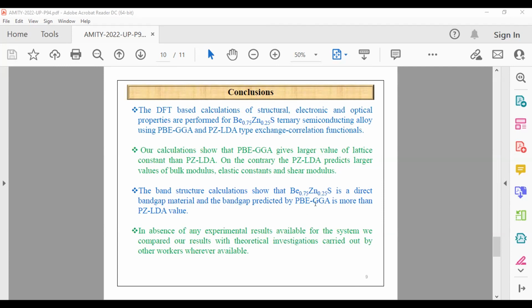The band structure calculation shows that this structure is a direct band gap material, and the band gap predicted by GGA calculation is more than LDA. In absence of any experimental results, we compared our results with other theoretical calculations, and we found that our results are in agreement with previous calculations.